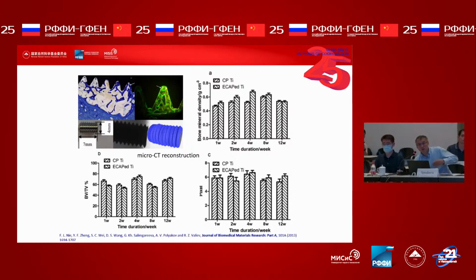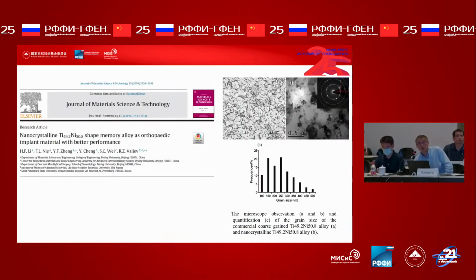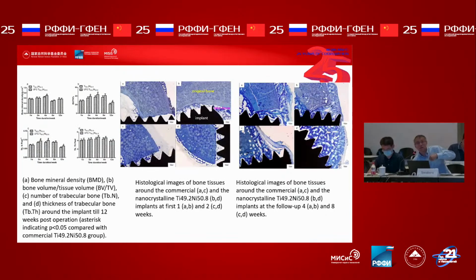Because we don't change the material, we don't change the chemical property or the chemical composition, but with this severe plastic deformation technique we can make the mechanical properties much better and even achieve better biocompatibility. Next slide. Later on, we also fabricated nanocrystalline titanium nickel shape memory alloys. It shows better mechanical properties. Next slide, please.